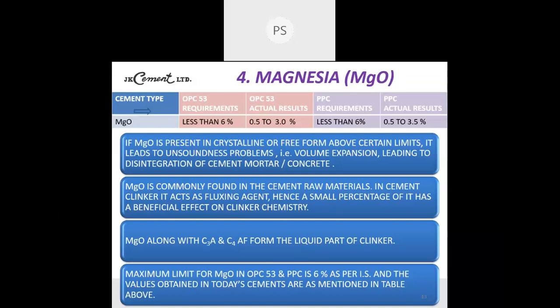Third point, MgO along with tricalcium aluminate, C3A, and tetracalcium aluminoferrite, C4AF, form the liquid part of clinker. Now, C3A and C4AF are two compounds out of the 4 compounds of cement. The 4 compounds of cement are C3S, C2S, C3A, and C4AF. So these two, C3A and C4AF, form the liquid part along with the MgO during the clinker manufacturing process.